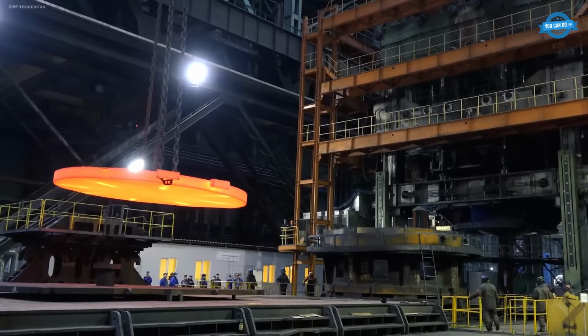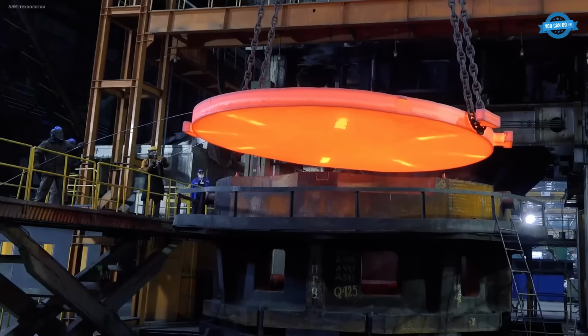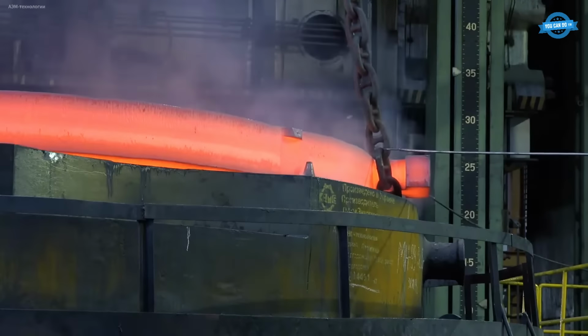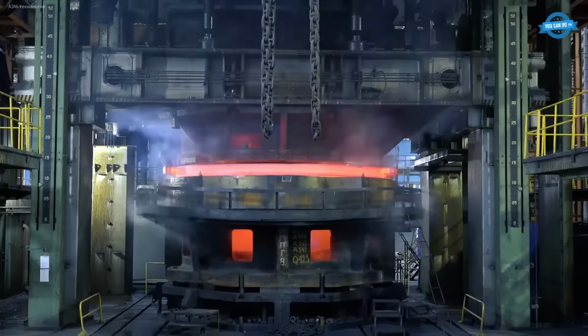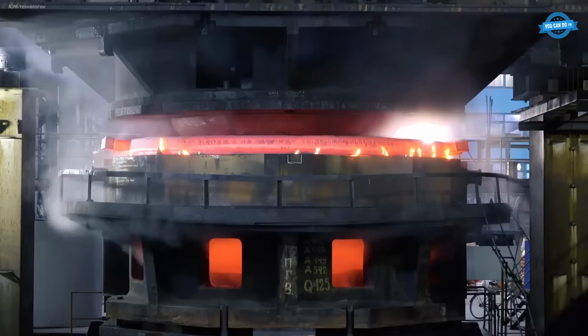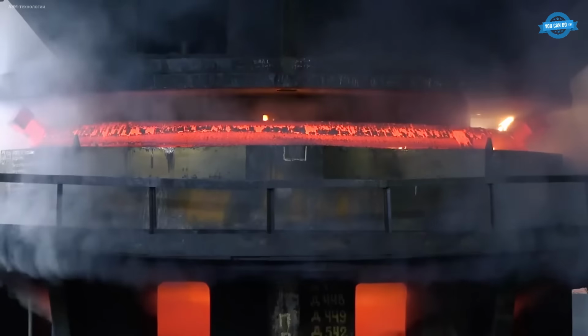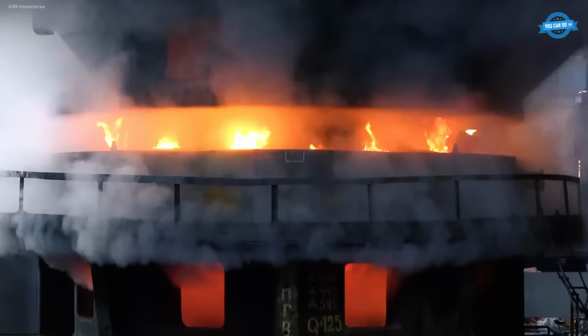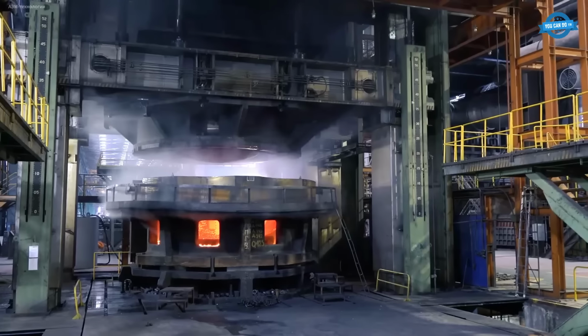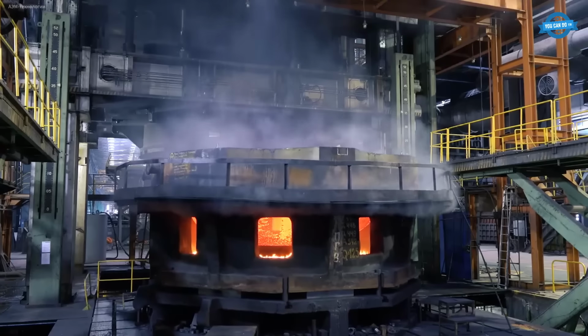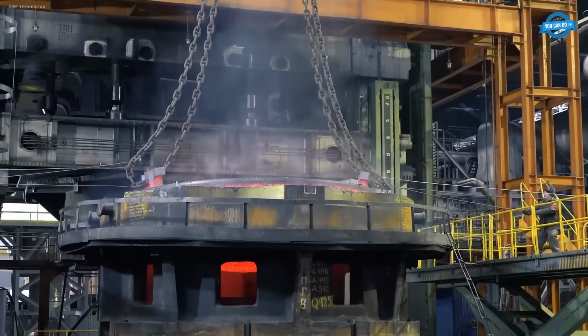The circular blank, weighing 64 tons and 300 millimeters thick, underwent a three-stage heating process lasting 6 hours, reaching a maximum temperature of 1020 degrees Celsius. After heating, the blank was moved by crane into the stamping die, where a press applied a force of 10,000 tons to shape the reactor bottom precisely.